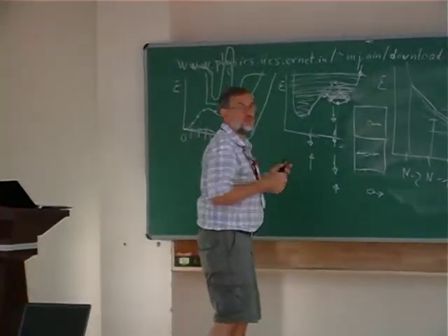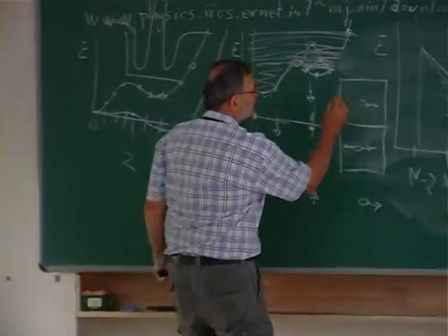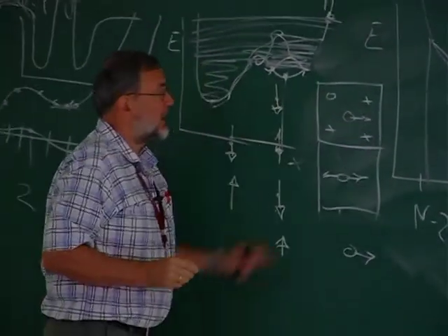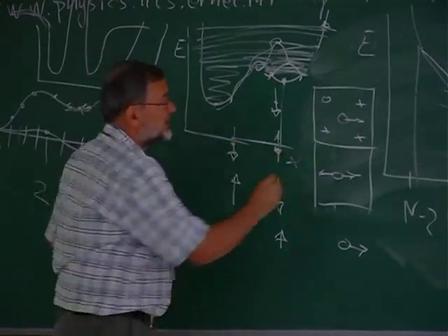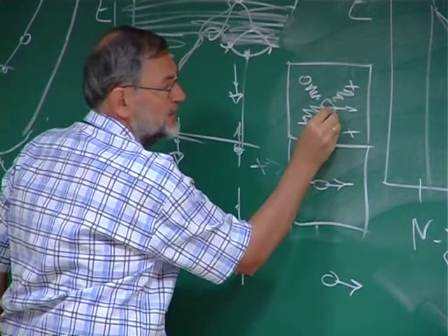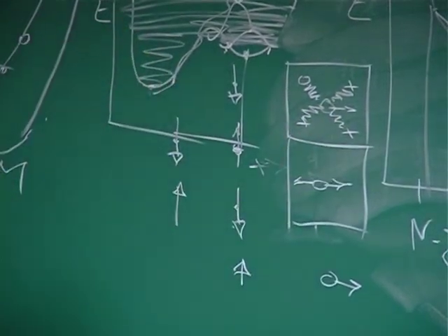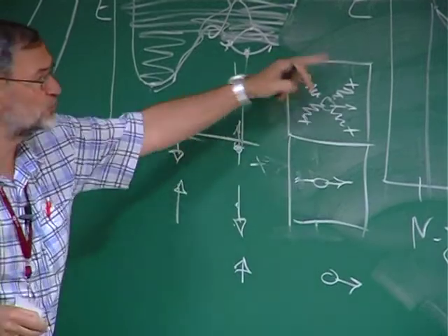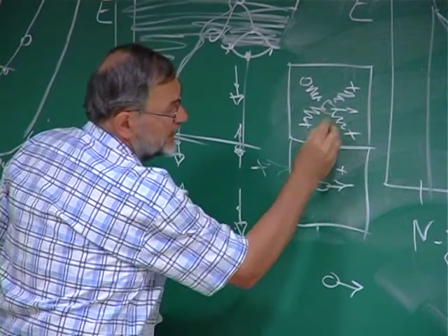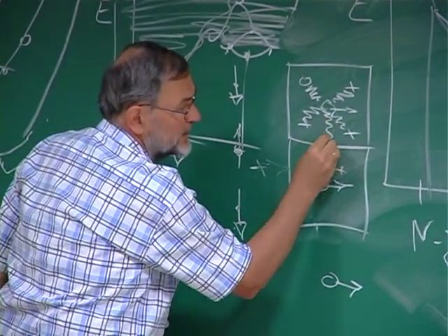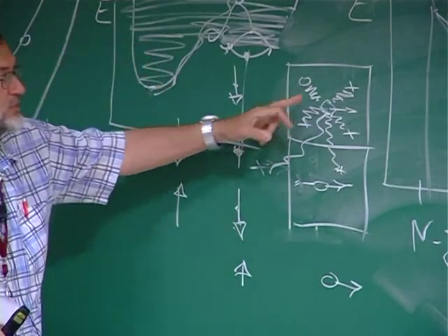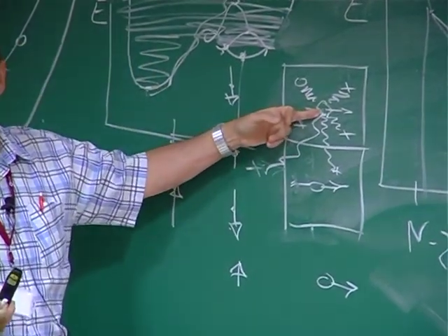We calculate then the so-called force constants. That means if I have certain atoms in my unit cell, I displace one atom, and I get the spring constant, the spring between these atoms. But of course, since my unit cell is so small, I also displace this atom, okay? And therefore I get also a spring to the next unit cells. And that I don't want, because I only know the total spring, okay?